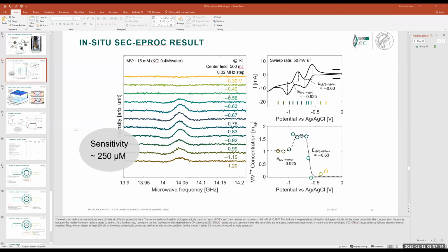So we used to use methylviologen all the time in photosynthesis research, and we moved away from it. We use ferro and ferricyanide instead. And you can see a color change if you do that electrochemically, and it has a nice electrochemical signature, CV. But it doesn't have a great EPR spectrum at room temperature, obviously, right? Because it's metal. Yeah. Right. So the other thing, just so that people know when you're handling it, to be careful and use as minimal amounts as you can, because it is actually really toxic.